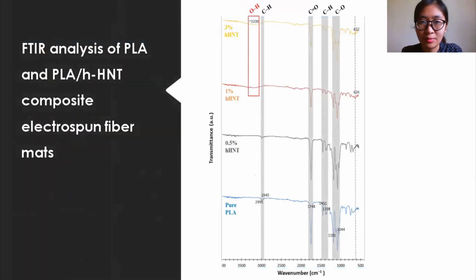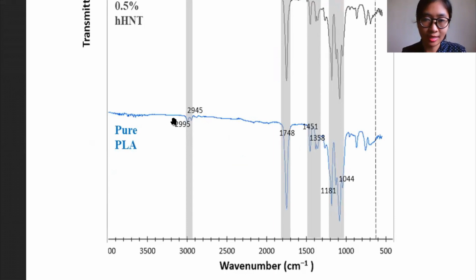Next is the FTIR analysis of PLA and the composite fiber mats. For the polymer matrix, characteristic peaks at 2995 and 2945 wave numbers can be attributed to a carbon-hydrogen bond stretch, while a strong peak captured at 1748 can be attributed to the carbonyl bond stretch of an ester. The intensity of the signal represents the strong dipole moment associated with the carbonyl of PLA.